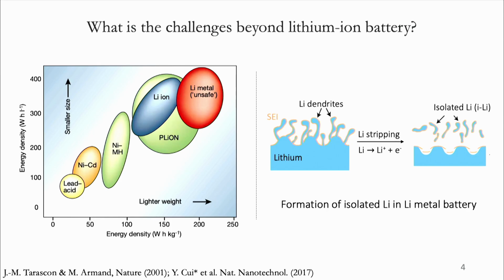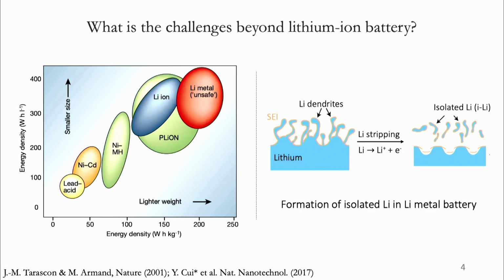Different from graphite, which is based on lithium intercalation, where between the graphite layers we have gaps and lithium ions can go in and out reversibly, lithium metal is based on conversion-based reactions. So lithium ions have to be converted into lithium metal. But instead of forming really flat and uniform thin films of lithium, what we often observe is the formation of lithium dendrites, those dendritic structures. During the lithium dissolution process, or lithium stripping process, a lot of those lithium dendrites become detached from the current collector. And that has been believed to cause fast capacity degradation, or short battery lifetime, with this kind of battery.